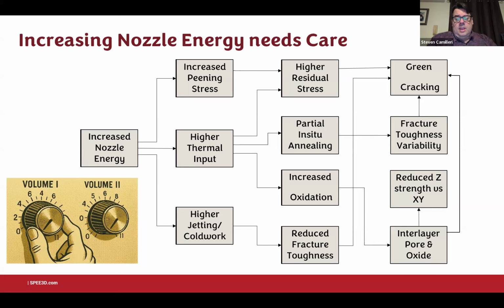Second one, there's a higher thermal input. So we're putting more heat energy from the gas jet as we cross across the part. So that has effects. Thirdly, of course, we're seeing more adiabatic shear. So as the particles are striking, there's more of this very highly plastically deformed zone being created as we increase the nozzle energy. So we see more of that kind of jetting and cold work type of microstructure.